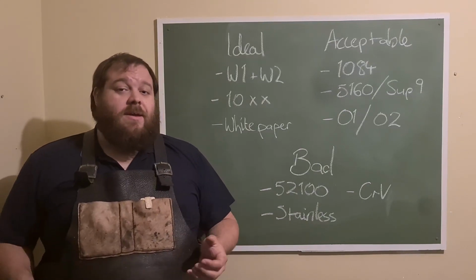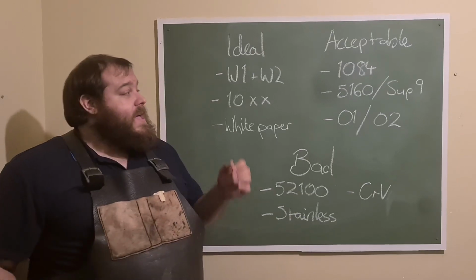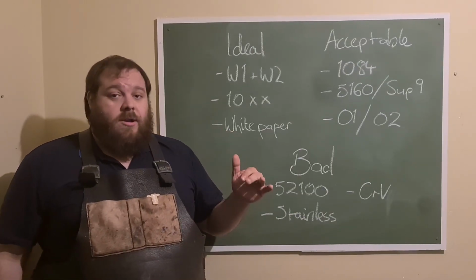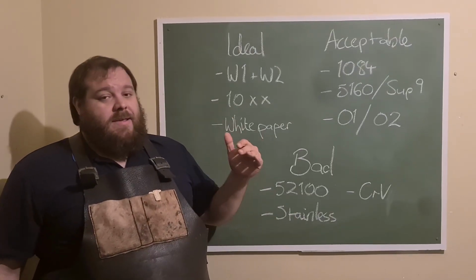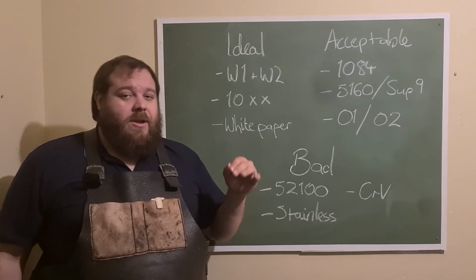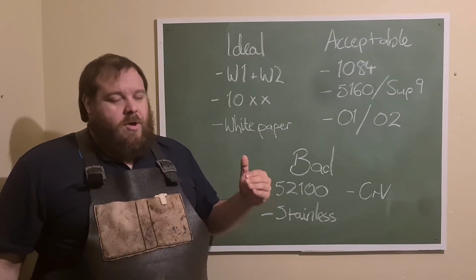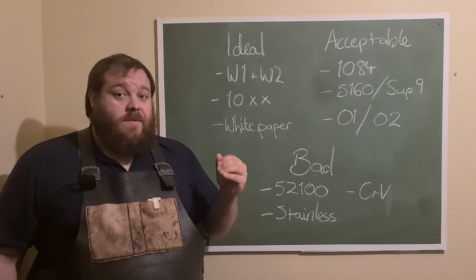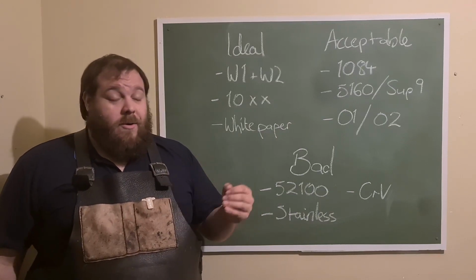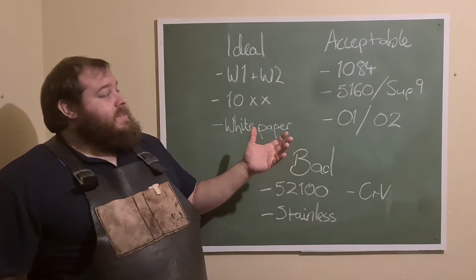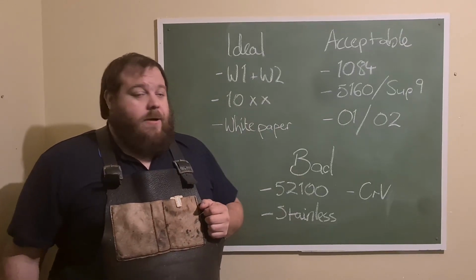I have a blade with Hamon in 1084, and it has some activity, but not a lot, because of the manganese content and that little bit of extra alloy content in modern 1084. A lot of the older stuff apparently was lower carbon, lower alloy, but modern 1084 does not take a Hamon that well.